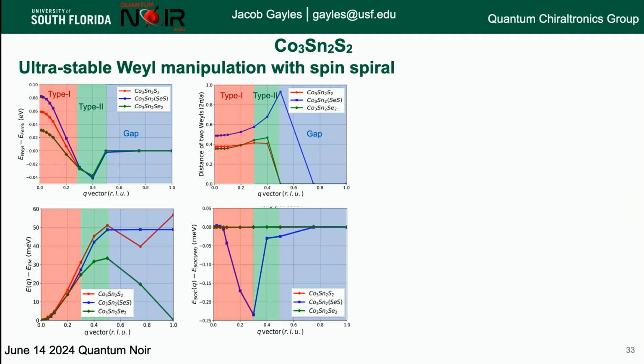So he's looked at the distance of these Weyl points and the energy of these Weyl points as a function of the spin textures. And he finds that it actually is very stable, which is a good thing for us because we want to not destroy these Weyl points with a magnetic field. This here is just the exchange that he calculated for his materials, which behaves nicely as a test to make sure that it behaves with the experiments.